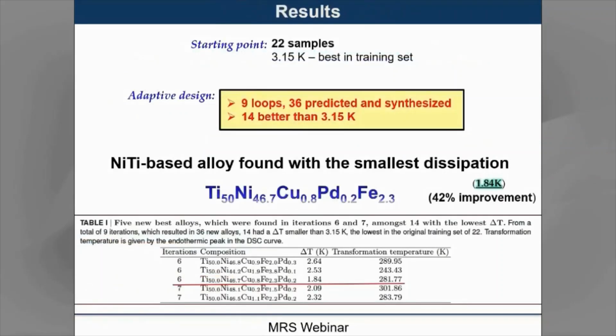Let me jump right into the results. So we predicted, synthesized, and characterized 36 new alloys in this particular process. Each iteration, we were able to make 4 new alloys. So we found that there were 14 new alloys with delta T smaller than 3.15 Kelvin, which was the best in our training set. And the best alloy, whose composition is listed here, had a delta T of 1.84 Kelvin, right? So this shows that our strategy in fact works, and we can in fact identify or predict, in this case, discover new alloys with properties better than what we started.